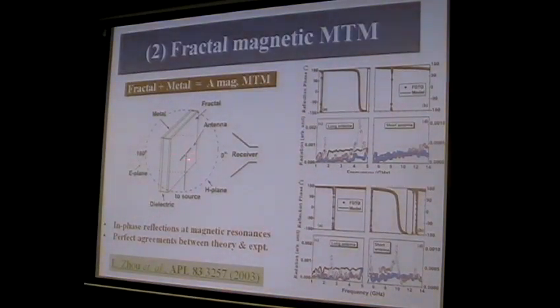So we performed an experiment to demonstrate this idea. How to demonstrate this idea? We attach a very small antenna just on the top side of this fractal plate. Because the radiation of this antenna is actually an interference between its own radiation and its reflected wave. If the reflection is out of phase like metal, no radiation can be detected in the far field. If the reflection is in phase, the interference will be constructive. That means that the total radiation will be strongly enhanced.